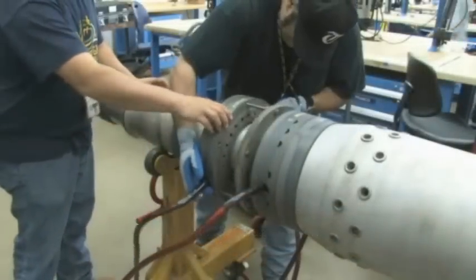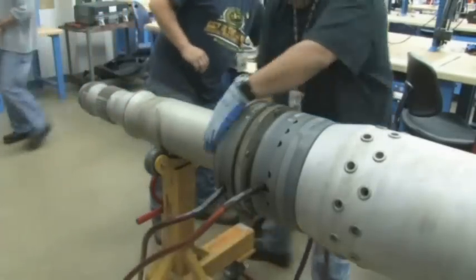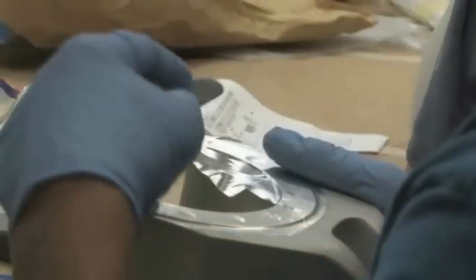You have a more efficient plating. You can get the part plated faster, sooner. The rule of thumb that we discovered in using the no-mask fixturing was that basically the plating tank dwell time is reduced by about 50%, sometimes even more than that.